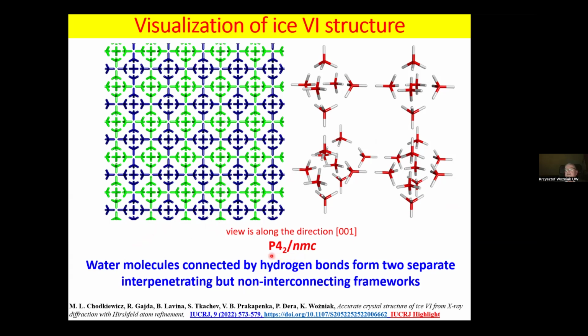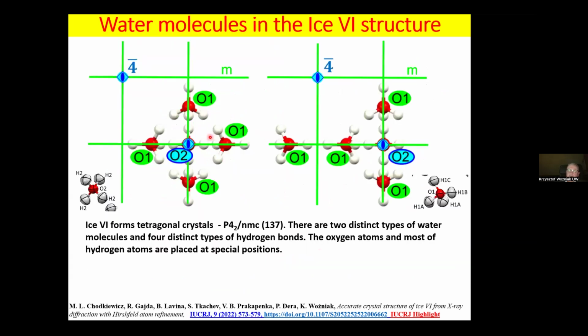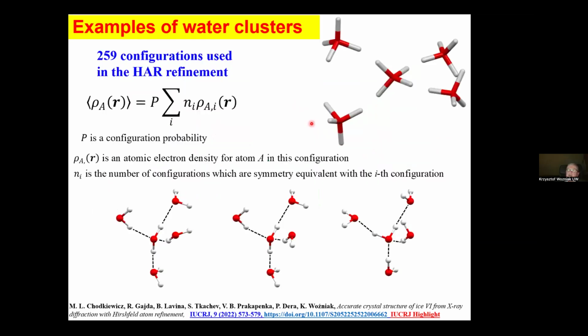And ice VI, which is crystallizing in the P42/nmc space group, we have water molecules connected by hydrogen bonds, which form 2 separate interpenetrating but not interconnecting frameworks. And you can see them in 2 different colors. In this crystal, we have 2 independent water molecules. One is occupying a special position at the -4 axis with 1 independent hydrogen atom, and the other one is staying at a symmetry plane, so thus it has 3 independent hydrogen atoms. So when you collect neutron data, and you refine them, you will see this kind of average structure.